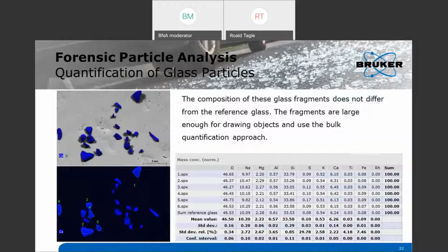So you can have a very large piece, which is actually very thin, whereas a smaller looking particle is maybe even thicker. And yeah, so if you do a mapping, you will be seeing where you have the representative part of the sample in these large areas. For these large samples, most of the sample area is representative.